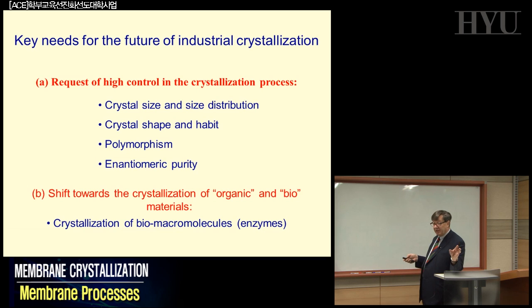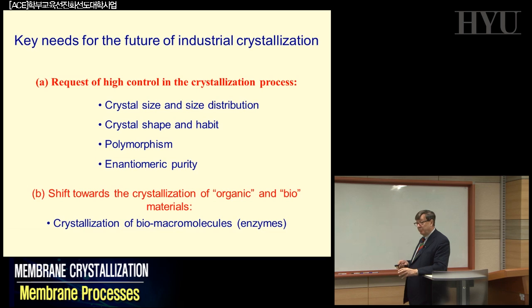Most of the crystals don't exist in one single habit. The same chemical composition can appear in different forms, and these forms can have very, very different properties, to the point that in some cases, some of these forms can be useful as a drug. In some other cases, they can kill if you have the wrong form. But in any case, they have very different performance at the end, just because of the habit.